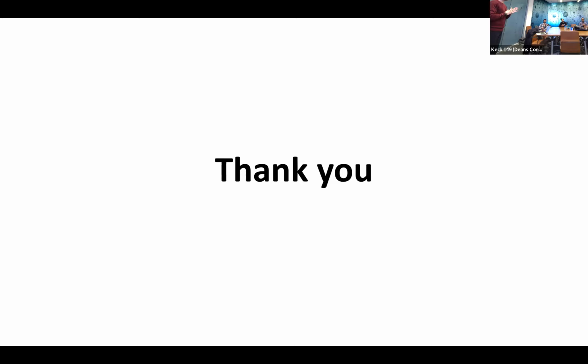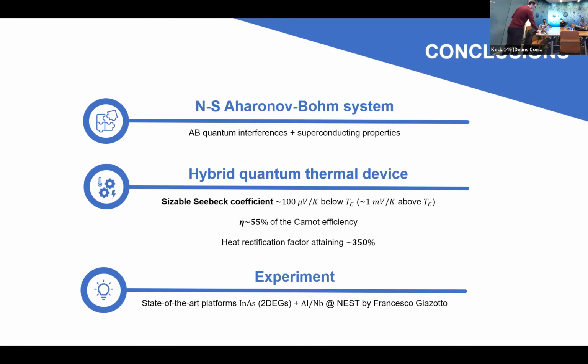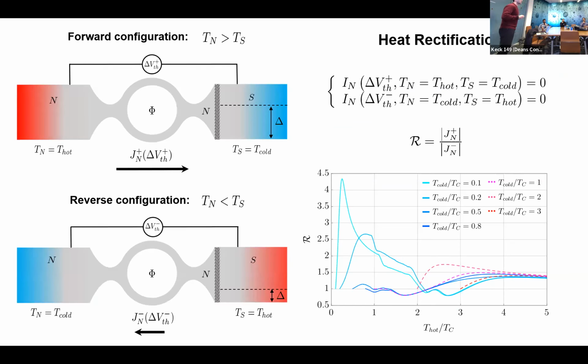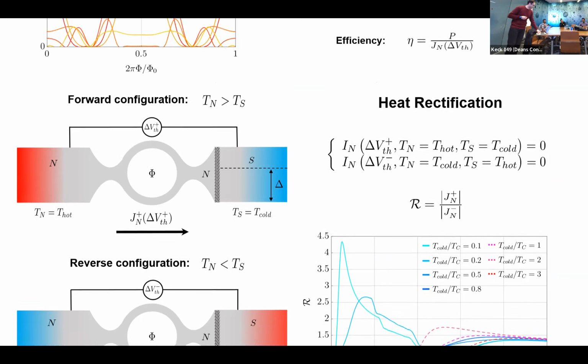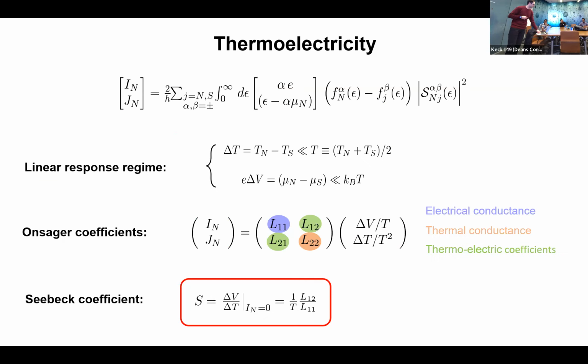So it was very clear to me that adding the ring greatly enhanced your thermoelectric response. However, I didn't get a simple physical reason for why. So if I think about just an Aharonov-Bohm ring, and I have just a simple voltage, I look at the electrical current. As I thread that flux through the loop, I get a characteristic sinusoidal pattern of current versus flux. And so I imagine something similar happens with the heat current.